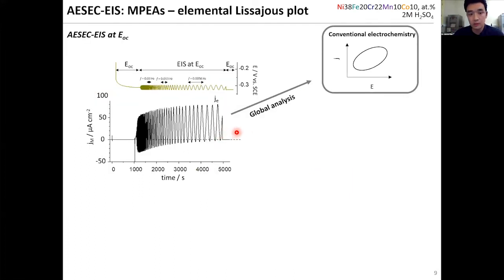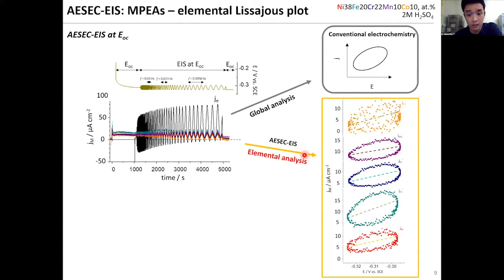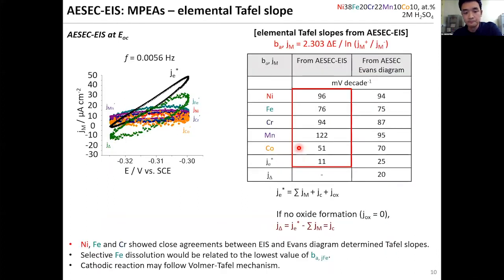So speaking about the impedance, conventionally we measure impedance spectroscopy, like oscillation of current and a Lissajous plot. But by AESEC, we can have more information, elementally resolved. So it is nicely oscillating in phase with the current density for this alloy. And we can also construct elementally resolved Lissajous plots for these 5 elements differently. So this is really an elementally resolved technique coupling, so that we can have more information element by element.